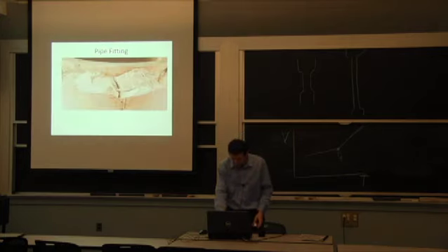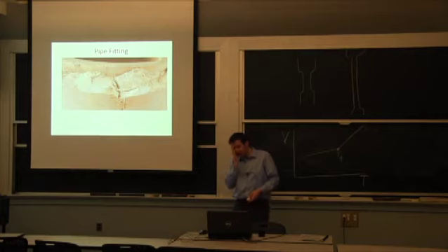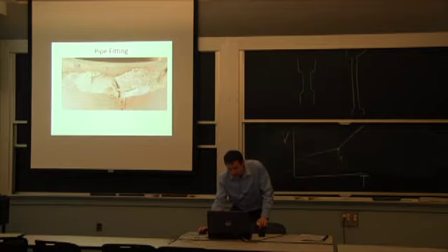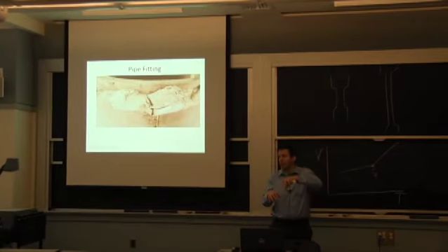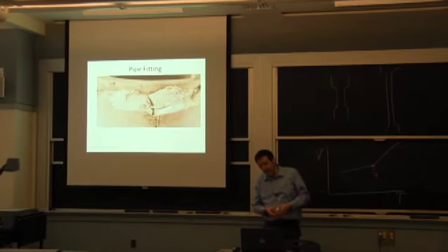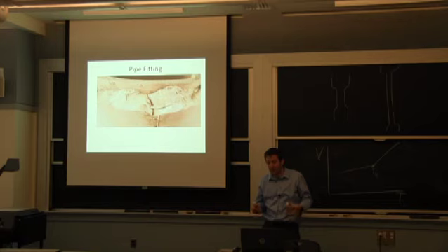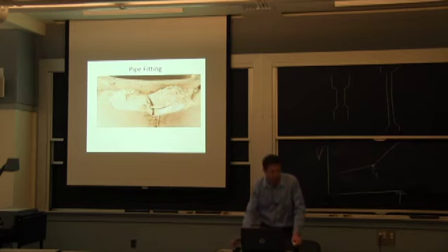So I want to go over environmental resistance. That's a PVC pipe that failed at the position of the solvent cement line. So we have a crack initiation here, a crack initiation there. We're looking at cracking of the fitting that's over the elbow. That happened over time. It was very slow cracking at the beginning, and then it progressed. There was definitely degradation of the resin by the solvent. And it's not atypical, like gasoline tanks are very well known to become softer and also more brittle because of exposure to all the solvents in the gasoline.